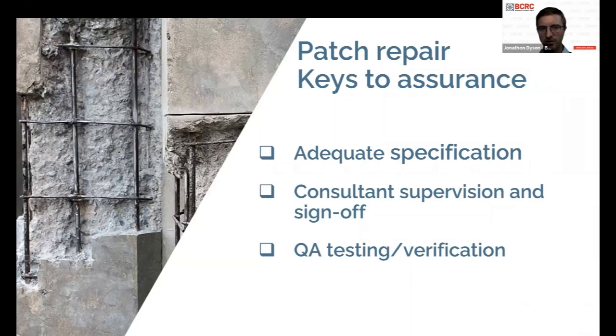Otherwise, you just can't be sure that they're actually being completed to the performance that has been expected and designed for. So you can sign off, you can certify those repairs by doing things like QA testing and verification that the repairs have met the performance that is needed. That could be things like pull-off tests or even things like non-destructive testing, UPV, to make sure that the area that's been repaired is no longer low density or porous, it's no longer got voids, etc., these sorts of things. And you can do that for crack injection repairs too.